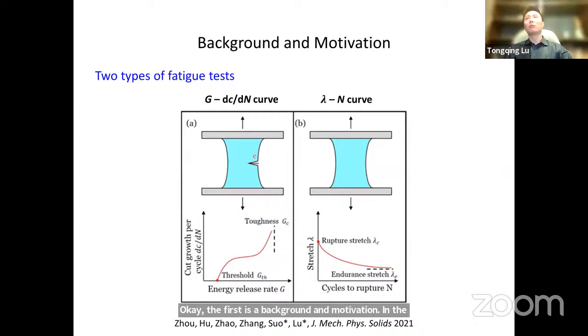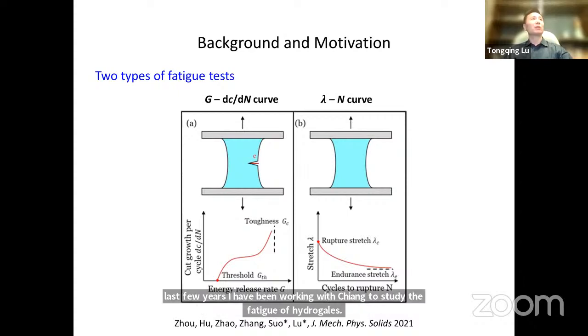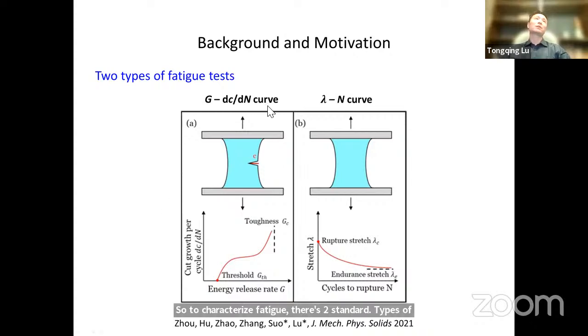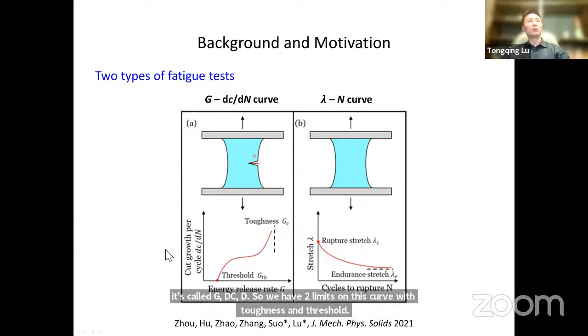In the last few years, I have been working with Zhigang to study the fatigue of hydrogels. So to characterize fatigue, there are two standard types of fatigue tests. The first type, the left one, is we put a precut in the sample and apply a cyclic load. And we record the crack growth per cycle, dc/dN, as a function of energy release rate G. So it's called the dc/dN curve. We have two limits on this curve, toughness and threshold. This method has been used widely in recent years to characterize fatigue of hydrogels.